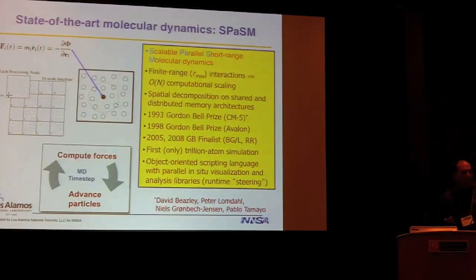But in between these two, at the atomistic scale, this is a particularly simple algorithm. It's one that's really useful for exploring different approaches on new generations of machines. And in particular, the code that I've worked with at Los Alamos is this so-called SPaSM code for scalable parallel short-range molecular dynamics. And the short range in here is the key. When we're looking at metals and organic systems, those interatomic interactions that I mentioned are fairly short range. There's a screening, so every atom only really sees its immediate neighborhood, and it only needs to know about the atoms nearby within some cutoff distance.